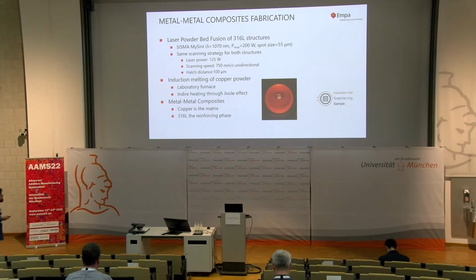So, as a first step, we use laser powder bed fusion, and more specifically the SISMA machine. I think that if you have seen already one presentation from EMPA, you already know about this specific machine, and we use the same scanning strategy for both lattices and cylinders. We played with a laser power of 125 watts. We used a unidirectional scanning strategy with a rotation of 90 degrees between the successive layers.